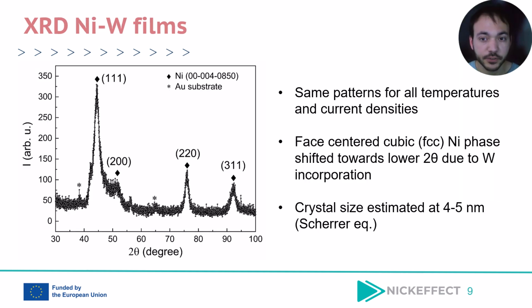The crystallographic structure of the nickel-tungsten coatings was studied by X-ray diffraction. The pattern shows peaks compatible with the face-centered cubic nickel phase. We can also observe that the nickel peaks are shifted towards lower 2 theta angles due to the incorporation of tungsten in the lattice, in the form of a solid solution. The crystal size estimated from the full width at half maximum of the 111 peak using the Scherrer equation is between 4 and 5 nanometers, indicating the nanocrystalline character of the film.